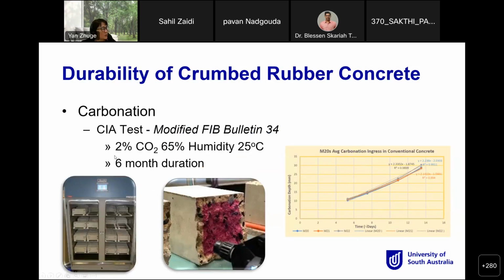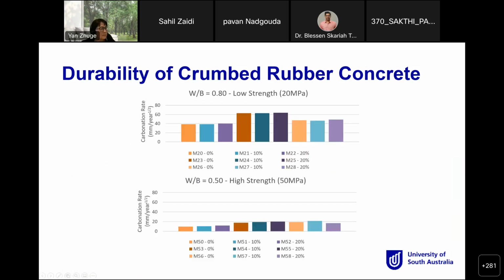Another test we did was the carbonation test. Based on the CIA test modified method, we have 2% of CO2, 65% humidity and 25 degrees. The test will last for about 6 months. So that is the results.